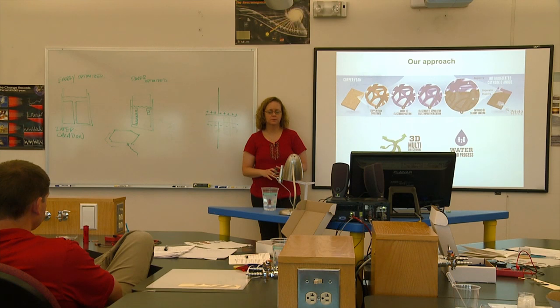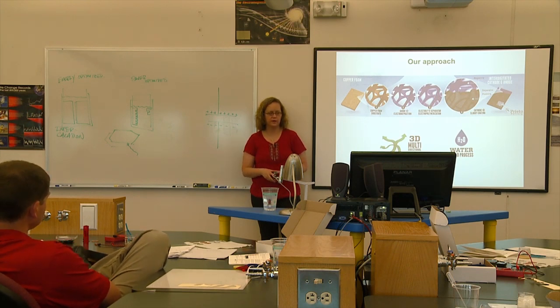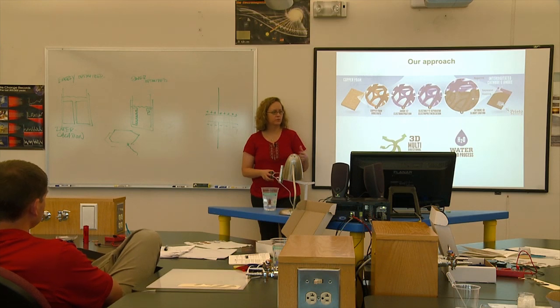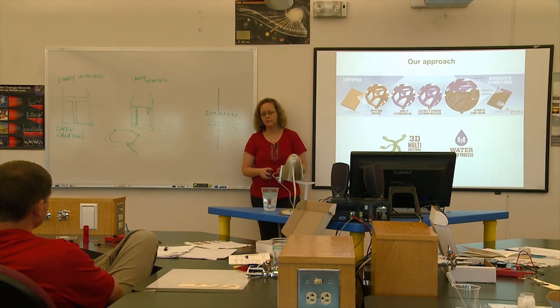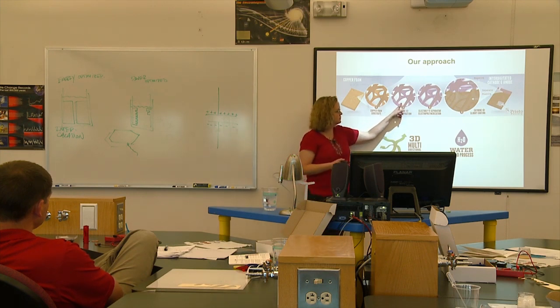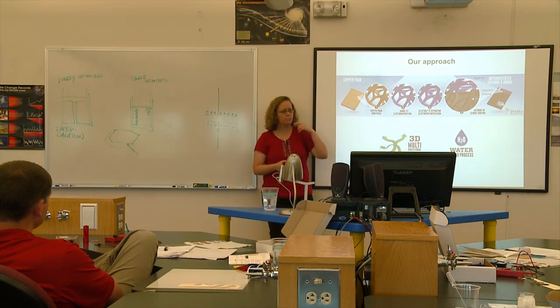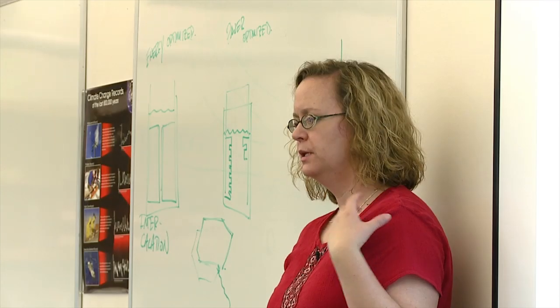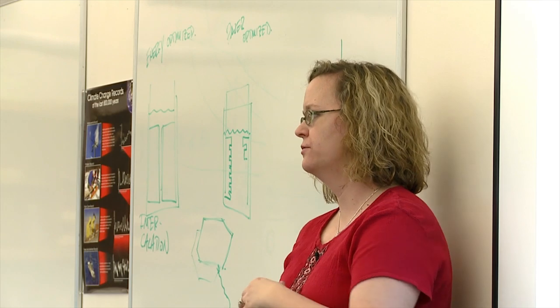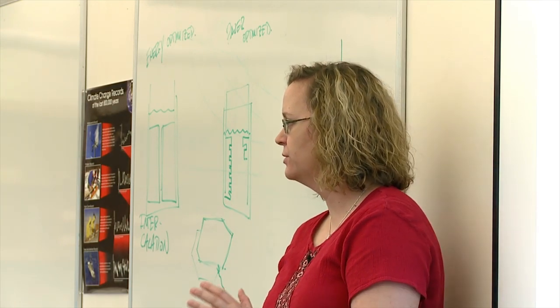It has to be stable at high temperature, because batteries get hot, especially if you charge or discharge them really fast. It has to let lithium ions go through, but it can't let electrons go through to high voltages. So normal lithium ion battery runs at about 3.6 volts. We've made our polymer stable up to about 8 volts because we figure there might be hot spots, especially where you see all these little curves. And we have to have a way to plate it so that it really does cover every piece of the battery, otherwise you get a short.